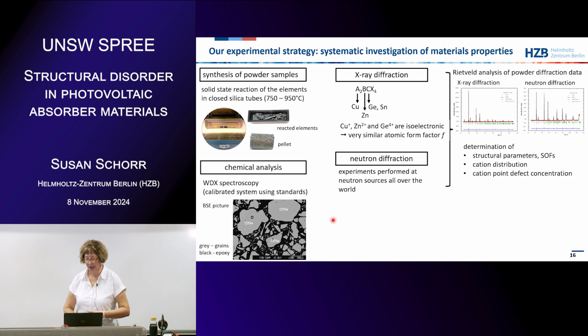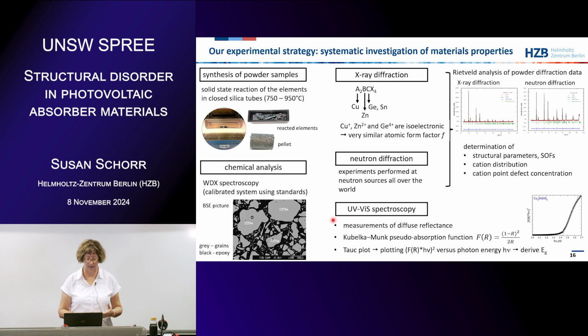We get the structural parameters we want, so lattice parameters, and especially the site occupancy factors. From them we determine cation distribution and the point defect concentration. Of course, from each powder we also determine the band gap by UV-vis spectroscopy. I think this is a method you're familiar with. We measure diffuse reflectance and then apply the Kubelka-Munk pseudo-absorption function to make this Tauc plot, which is shown here. And then from the slope here, you can get the band gap value.